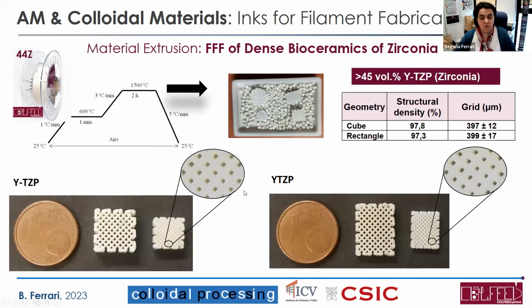After the thermal treatment. And we can do that, of course, also with another kind of ceramic particles like zirconia, for example. You see here that we have 45 volume % zirconia in our filament. That means that we have 40% of shrinkage after the thermal treatment and sintering, right? But the shrinkage is really well controlled and gives us a very good dense material, right? Close to 98% of final density, right?